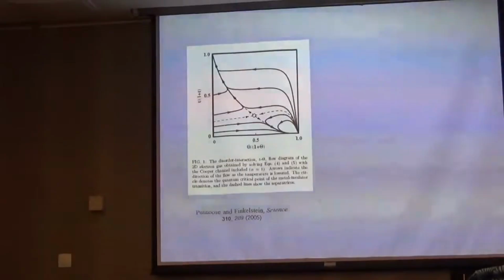So that's a phase diagram. It may look strange, these coordinates, but in fact you can consider the x-axis as interactions: zero is no interactions, and then infinitely strong interactions. And the vertical axis is the disorder resistance. Don't pay attention to the right top part of the phase diagram because it cannot be realized in the experiment. But you can see what happens on the left side of this line. At first, when interactions grow, resistance goes up and then it goes down and eventually should approach zero. But only if disorder is not too strong.